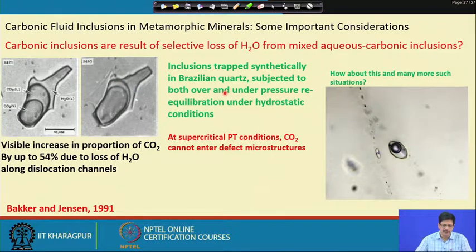That led to the belief that in many of the situations where we see pure carbonic inclusions in the samples, it may be because water would possibly have been lost from the inclusion cavity along such crystal defects or lattice dislocation planes. But then